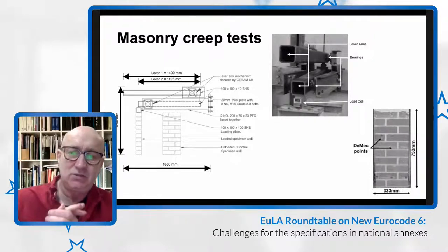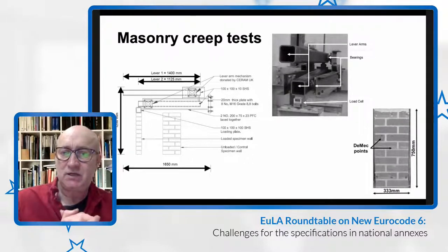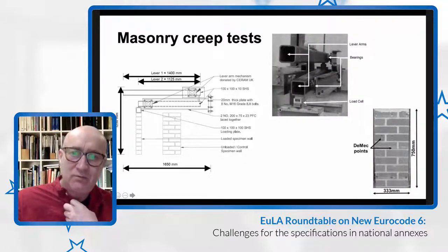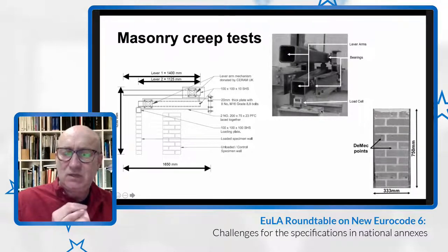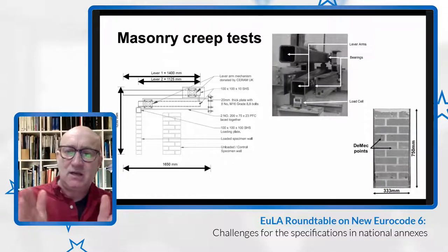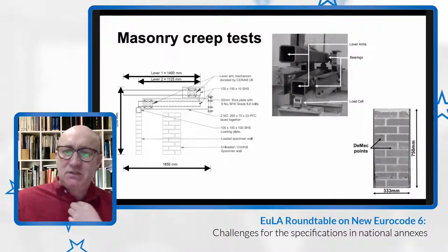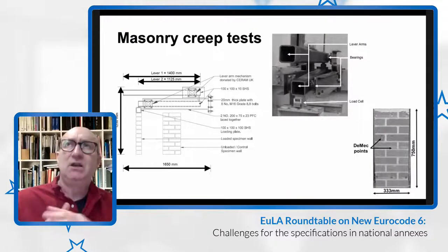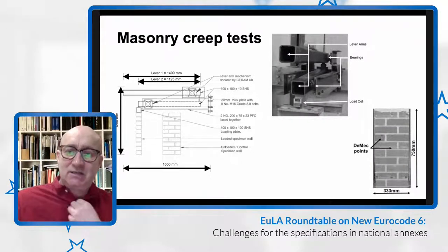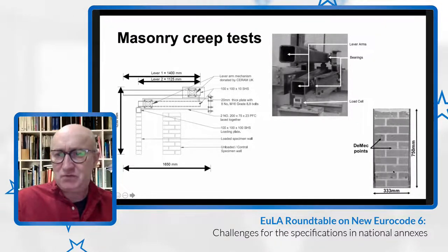And in the initial testing we went to quite a lot of trouble to try and get the load on the wall as concentric as possible. So here there's a load cell, and then we have a stiff steel spreader plate at the top here to try and get a uniform stress. And we did some adjustments before. So there was some initial loading, unloading, and adjustments to get a uniform strain in the walls. But it was very difficult to achieve.